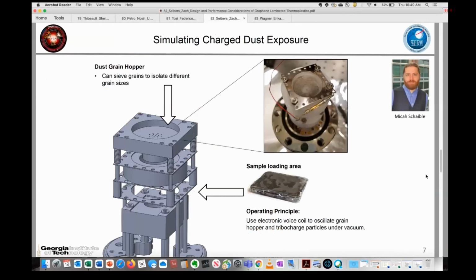So to look at this a little bit further, we took some various samples, we being my colleague Micah Schaible, who's also in the Reveals research program. We put them in a special chamber that he's built for his work. I'm asking for a little bit more out of his environment than what he originally built it for. But the idea here is we can take dust, charge it with tribocharging or with an electron source or something like that, and drop those charged grains down onto the surface. We can apply a voltage to the surfaces, and we can apply electric fields to the whole assembly. We are using JSC-1A, and it's dried in vacuum and with heat before it goes in. So these are pretty representative samples, doing the best that we can with this apparatus.